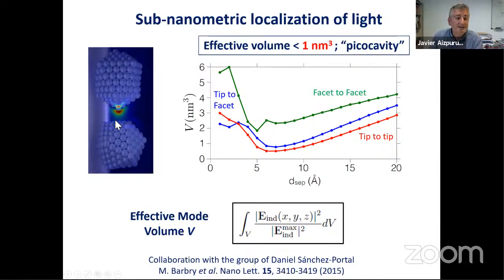And this pico cavity is nothing but the photons trapped at almost a single atom level in a metal, combined with the whole collective oscillation of the plasma here. I mean, if you put just one atom here, you will get a very small polarizability of this atom. But this atom mounted on top of the whole plasmonic oscillation provides this extra factor that provides this confinement.